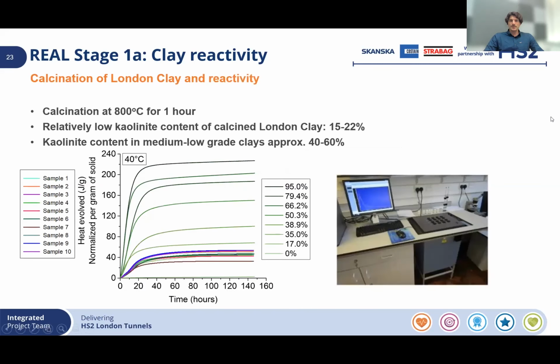We moved on to calcine the clay at 800 degrees for 1 hour, and then we carried out some heat generation monitoring. This is through isothermal calorimetry tests, measuring heat evolved in paste samples. Not to get very technical, the lower the heat evolved during that period of testing, the lower the indication of kaolinite content. So we compared these results with existing literature results. In this figure, the green lines represent kaolinite contents, and the colored ones represent our samples.